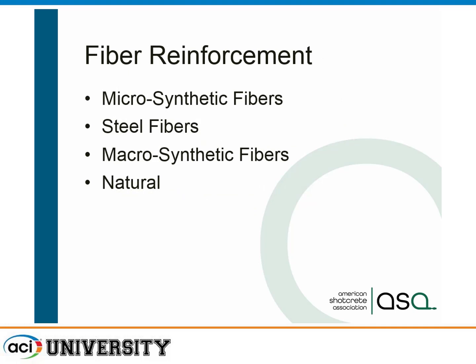Fibers, we use microsynthetic. Those are used a lot for control of early age plastic shrinkage cracks, which is a problem in a lot of our repairs, right? Where the surface is exposed to air, wind, might be a dry climate like here in Las Vegas. And so the microsynthetic fibers help to control the early age plastic shrinkage cracks. When we get into more structural applications, we do use steel fibers, and then the macrosynthetic, which is a longer, bigger diameter fiber. Those are actually about as effective as steel fibers in providing resistance against more of the long-term cracking. Mentioned here, natural: we've also been using hemp fibers that actually hold some water, provide some internal curing, which is really good for a repair job, because it's almost like internal curing of your repair as well as external, so you're going to get less shrinkage cracks overall.